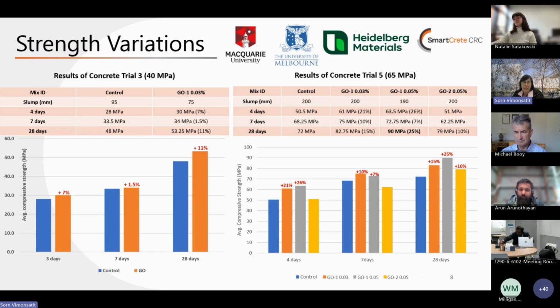With the content of graphene oxide being 0.03 and 0.05, we found that the best mix was with 0.05% graphene in concrete. At the 65 megapascal grade, we managed to get about 25% increase, but that is only for that particular mix. That's why there is still a bit of variation in these results. So we have to look at the trend from the early strength to the 28-day strength. This is what we've got so far.